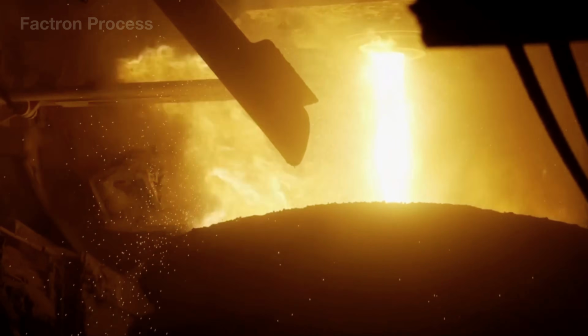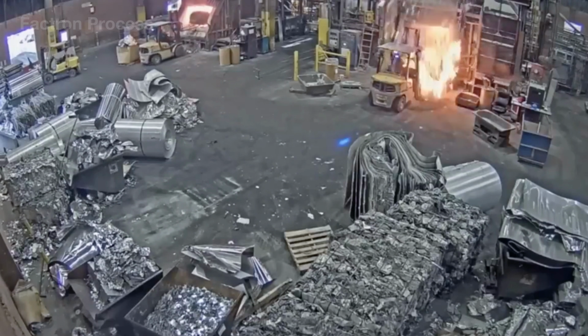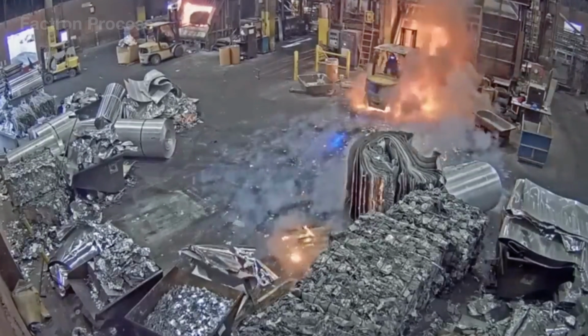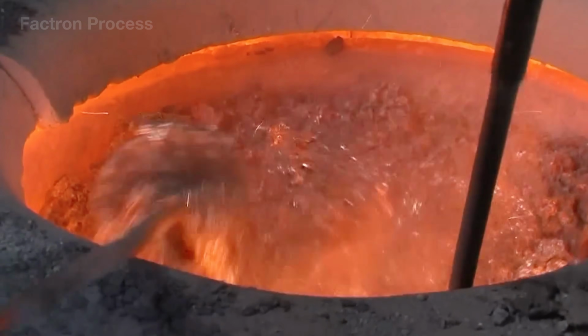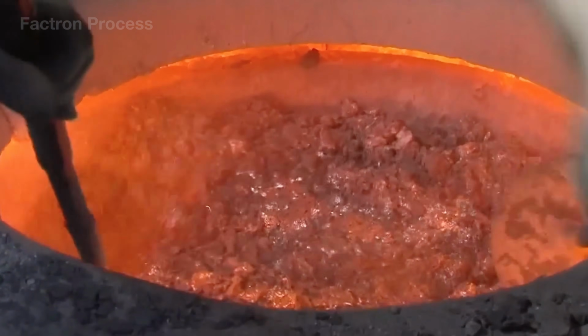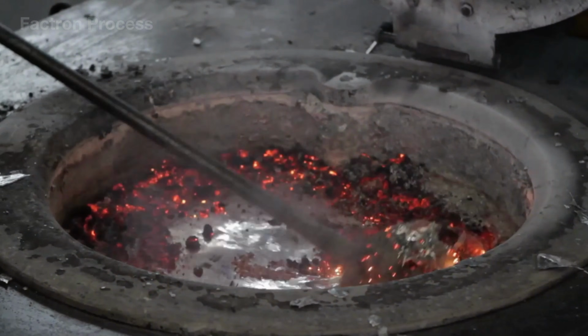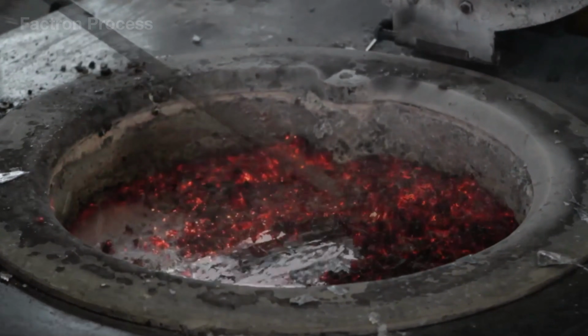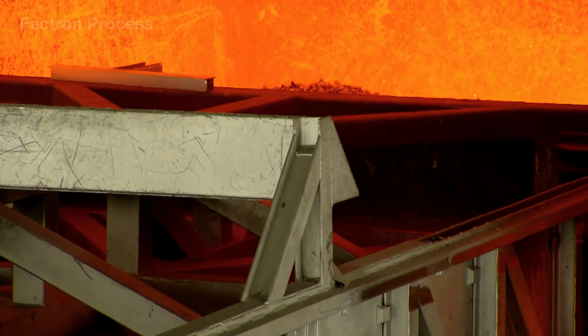Its alloy composition must first be tested and carefully adjusted by adding precise amounts of magnesium, copper, zinc, or silicon to achieve the required mechanical properties. Even a small imbalance can reduce the recycled metal's strength and corrosion resistance or make it excessively brittle.